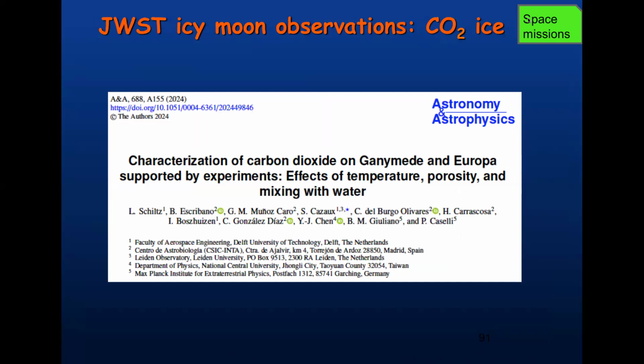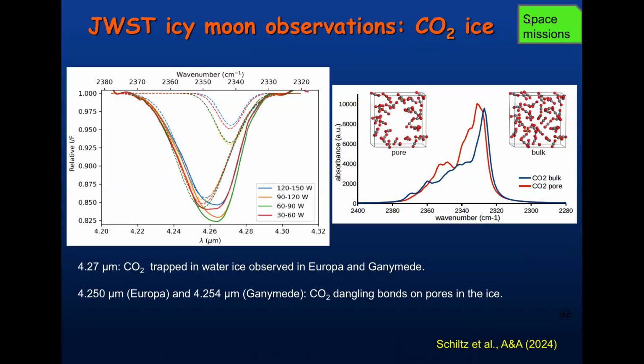So we used, with Stephanie Cazaux, recent James Webb data in Europa and Ganymede. And we have published that paper. One of the things we have learned is that with the infrared observations, you can say something about the porosity of ice. So in particular, in the DFT simulations, you can make a pore in CO2 ice, and you see the effect of the pore in spectroscopy. So this band here is not there if there is no porosity in the CO2 ice. Because this band here is observed, we think that there is porosity in the CO2 ice in Europa and Ganymede.